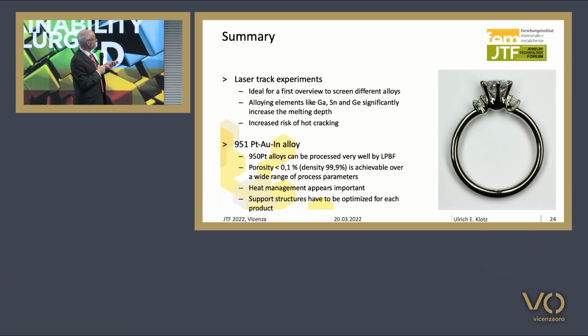In terms of the alloyed powder that we used, we found that we can achieve very low porosity levels over a wide range of process parameters. However, it appears important to do a proper heat management of the part, so it requires careful analysis of which regions need support structures, and this is especially important if you have many different parts that you want to produce. So there are rules of thumb, but it's better to test them if they are working for your particular part.